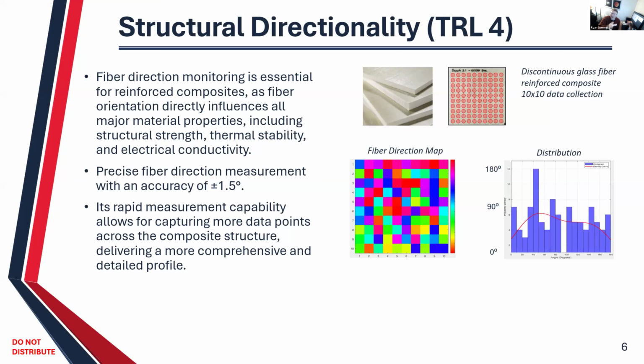We were able to provide this full field inspection methodology. So we have orders of magnitude of rapid inspection that still falls well within the accuracy. Now, again, if you see an area of interest that you want to dive deeper into, that's where we suggest you go into stage 2. Now you bring in X-ray CT to help complement this inspection and have a full understanding. But initially, you can utilize our vision technology as a stage 1 inspection to get full field of view, full coverage of your components.